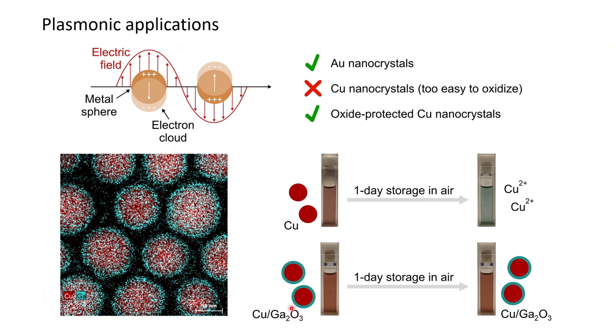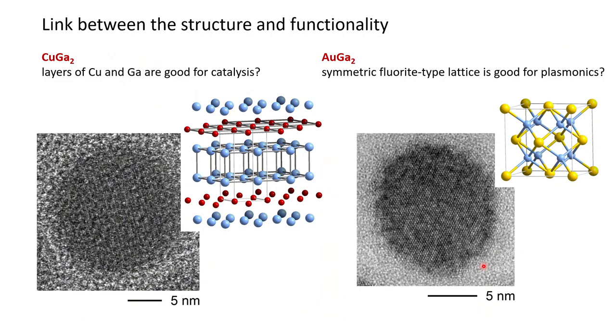But the gallium oxide protected copper sustained the plasmonic properties at the same conditions. It's, of course, more to come for the intermetallic nanocrystals.